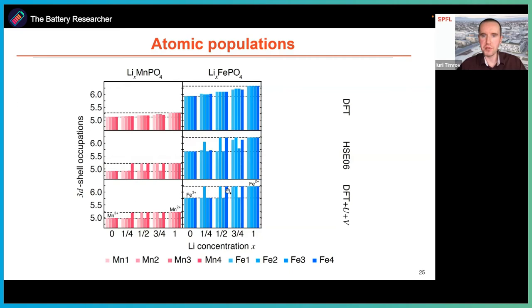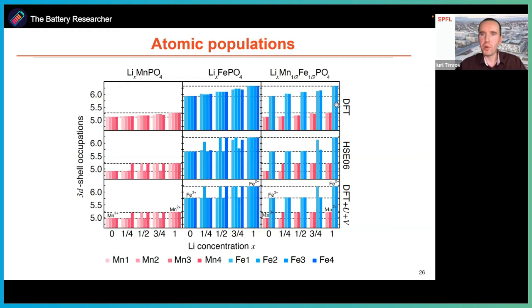Finally, if we consider the mixed case, where we have 50% of manganese and 50% of iron, we see that from 0 to 1/2, it's manganese that is changing its oxidation state. And from 1/2 to 1, it's now iron that changes its oxidation state. And again, for manganese we see digital change, while for iron, hybrid is not very accurate, while DFT+U+V is very accurate.